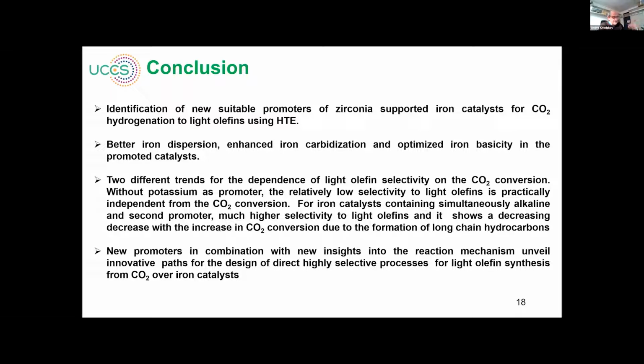Without potassium, the selectivity is low and practically independent of CO2 conversion. And for iron catalysts containing potassium, alkaline elements, and second promoters, we can clearly see maybe 3 times, 4 times, 5 times higher selectivity. However, the selectivity decreases with conversion, because of further polymerization and production of long chain hydrocarbons. So these results, the new promoters, in combination with new information on the reaction mechanism, can provide new paths for designing a new process for light olefin synthesis from CO2 on iron catalyst.